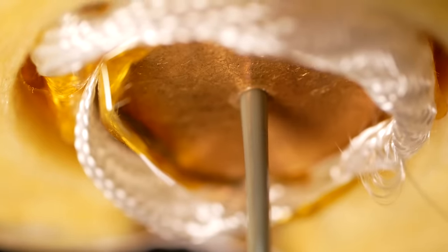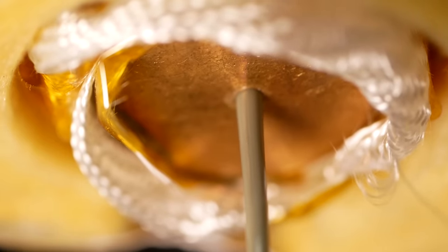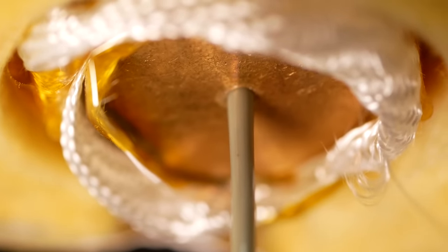Normal PLA pellets are usually extruded at around 160°C in the filastruder which gives you a slightly undersized filament with a standard nozzle and works perfectly in basically any 3D printer if you increase the flow multiplier a little. Running my first tests I noticed that if I run the recycled filament at these low temperatures some particles don't perfectly melt and give the material a grainy texture.